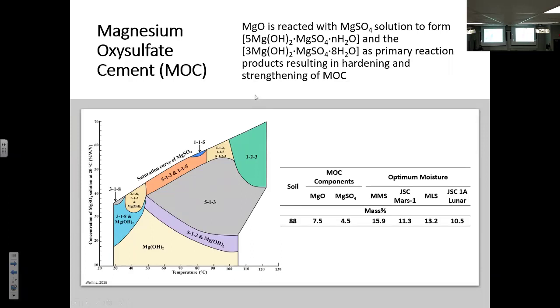The magnesium oxysulfate cement is a pretty straightforward reaction. We react magnesium oxide with a magnesium sulfate solution, and depending on the temperature at which you're reacting these two materials and the molar concentration of magnesium to sulfate, we can come up with various phases. It is a solid solution that is a hydrated phase. And so you can come up with all sorts of different compositions. But our target has been the 3-1-8 and the 5-1-3 phases. These are known through literature to have much higher hardening properties. They have high mechanical strength.